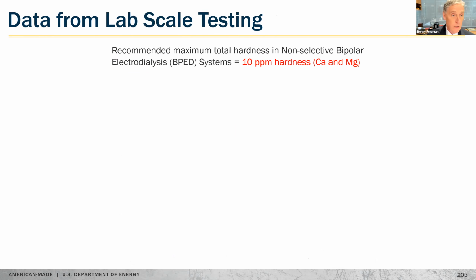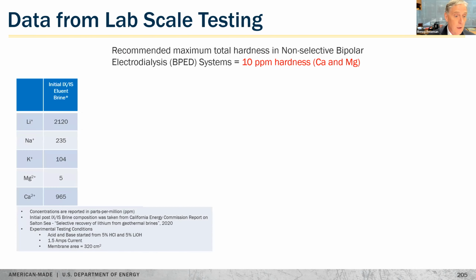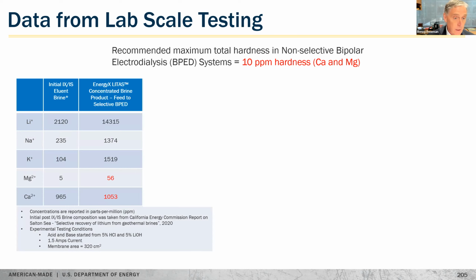Just by way of background, most manufacturers will not sell you a system for bipolar electrodialysis if there's more than 10 ppm hardness in the stream, and some even knock that down to 1 ppm. Next slide. And so we pick up in a model brine system, brine that has passed through an initial ion exchange process. You can see the composition here. Next slide. We have spiked it with additional magnesium to understand better the behavior of these divalents.